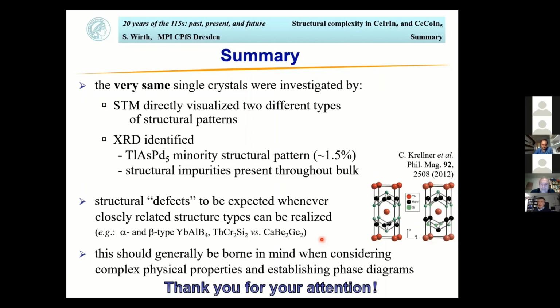If you look carefully at the numbers, the 1.5 was done for the cobalt with the 1001 pattern without any averaging, and if you do the same thing for the iridium, you end up with 1.2 percent of the impurity phase. So there is a difference, but we are here looking at the limits of the XRD, so I would say all of this is within the error bar, and I really wouldn't put any emphasis on the numbers.